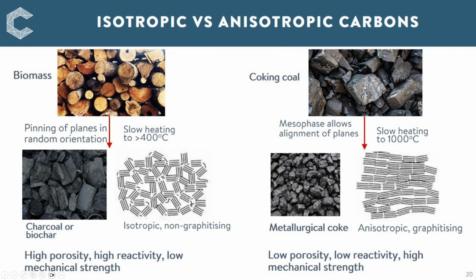Coking coal passes through a fluid phase when it's heated very slowly, known as the mesophase. And because coal of this specific rank and maceral composition will have a certain amount of tar produced, it forms this mesophase that allows these crystallites to start to move and align before it solidifies into coke. So coke is actually an anisotropic carbon where you've got this general alignment of the crystallites, and this is characterized by low porosity, a low reactivity and a high mechanical strength. So in the blast furnace, where it's got to survive to the bottom of the blast furnace and provide strength for the burden of material that's in the bed, it's a perfect material.